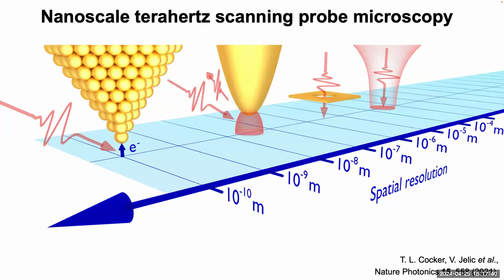In fact, if the dielectric function under the surface is different, a metal or something else, the oscillating field of the terahertz pulse looks different. If you take the Fourier transform, you see a resonance or whatever, that impacts how we model our terahertz STM data. So there are multiple reasons for this. One, we can't model things correctly unless we know what the waveform looks like over a given substrate. On the other hand, if we can identify our signals at the tunnel junction with atomic resolution, by being able to measure the waveform, then we can do spectroscopy. Like I started my PhD doing pump-probe terahertz spectroscopy, but now on the atomic scale.